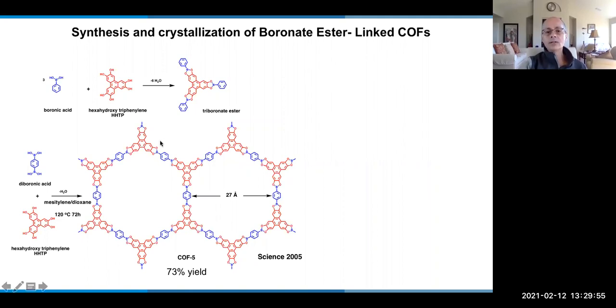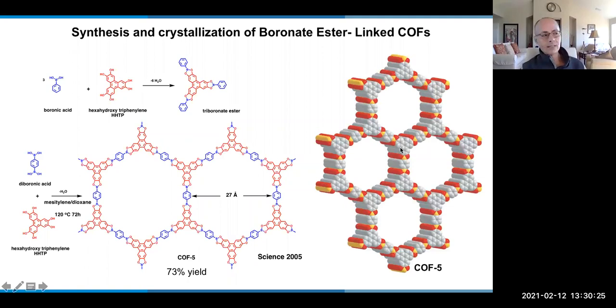Well, the same reaction conditions could be used by taking diboronic acid and copolymerizing it with this hexahydroxytriphenylene, under the same conditions, mesitylene and dioxane, 120 degrees, 72 hours, to make the expanded pore structure. Now the linkage is a boronic ester, or a boronate ester, I guess the proper name for it. The structure here is not a staggered layered structure, but an eclipsed layered structure.